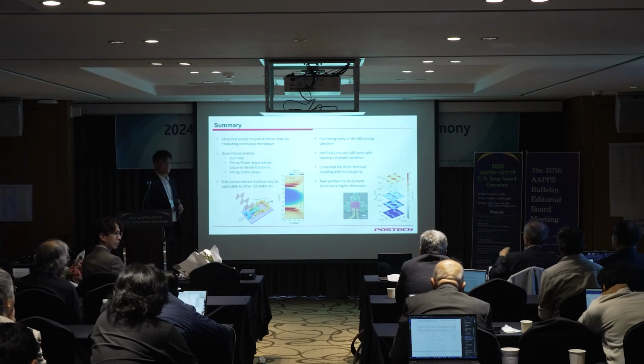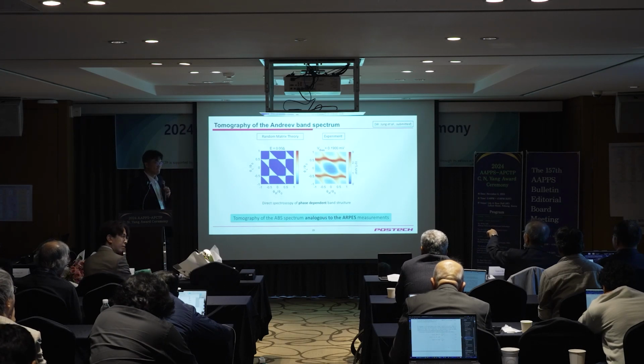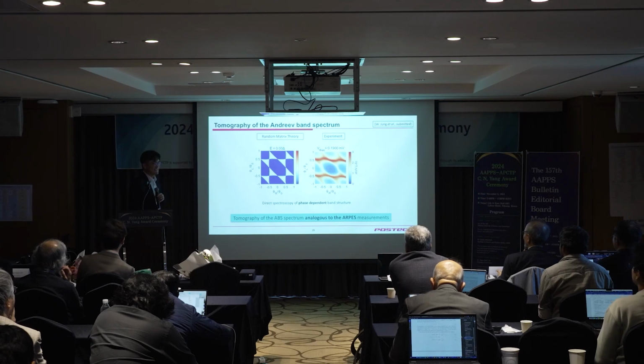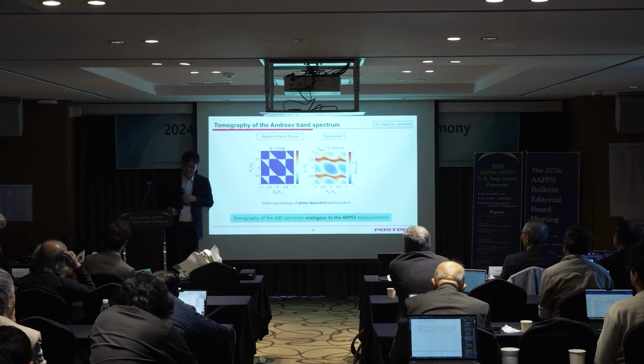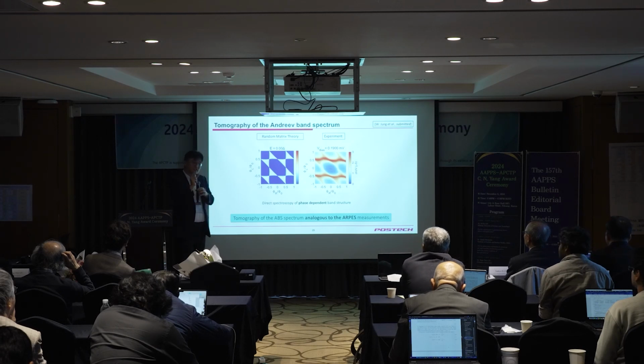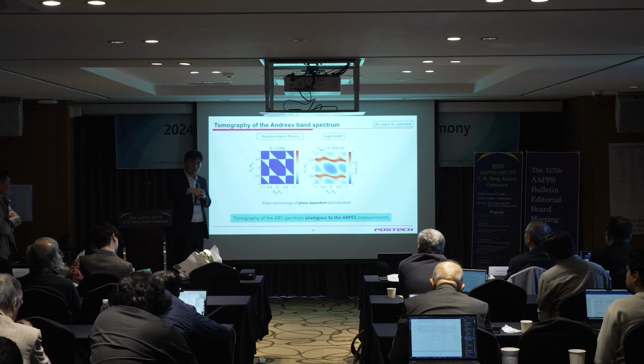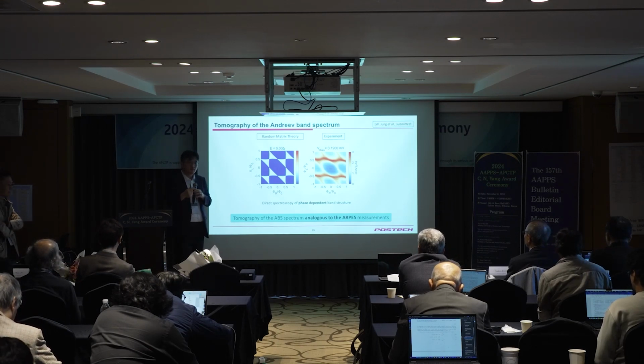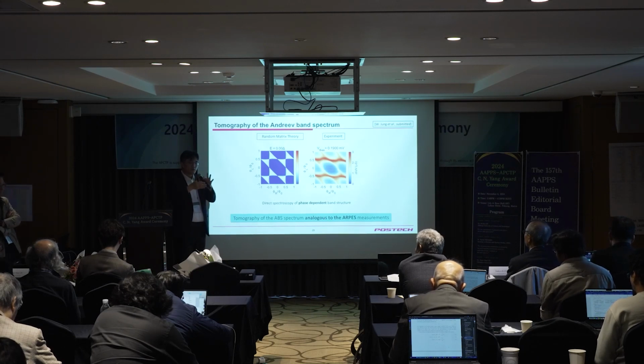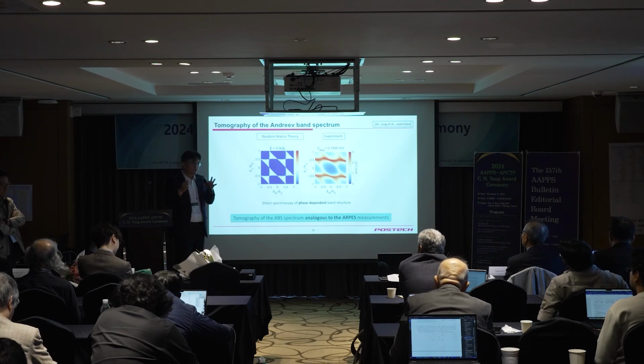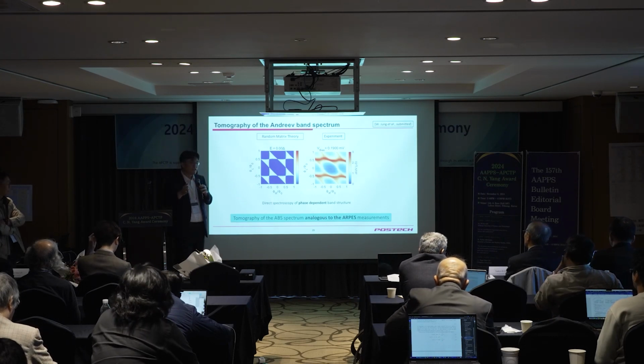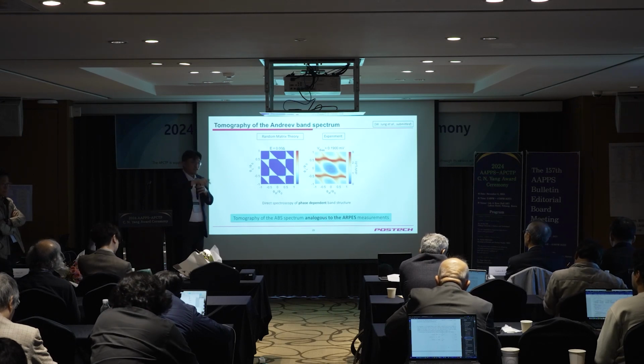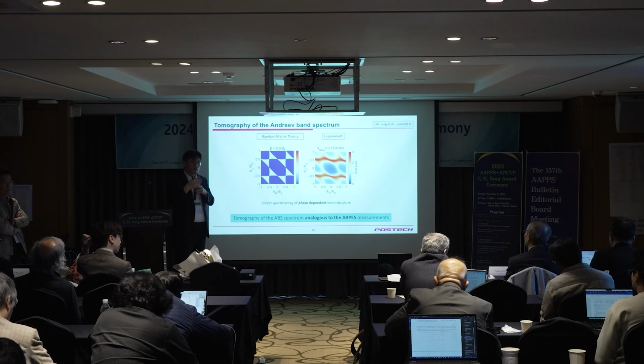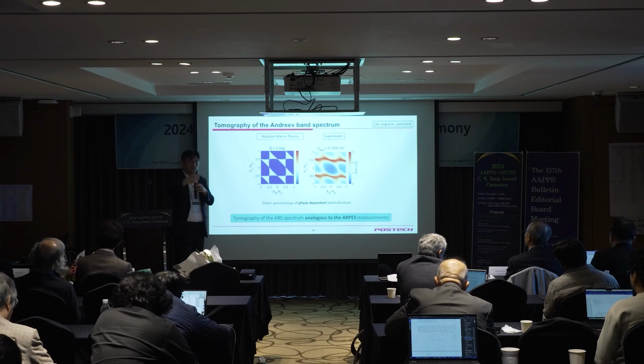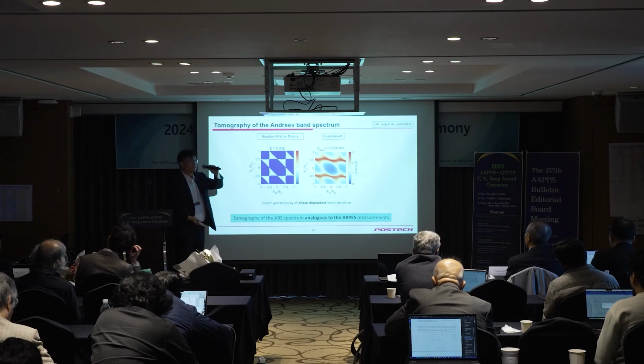Please. At the very end, you briefly mentioned this random matrix theory. Your system is not a random system. How does it connect? The thing is, the graphene size is about 1 micron, and the Fermi wavelength of the electron is on the order of 50 or 20 nanometers. If you divide 1 micron by 20 nanometers, there are 50 states, and there are 4 degrees of freedom, so 200. So there are hundreds of conducting channels inside the graphene. You have to think about a few hundred different scattering matrices. Each makes a different Andreev bound state, and what we are measuring is basically a sum of that.